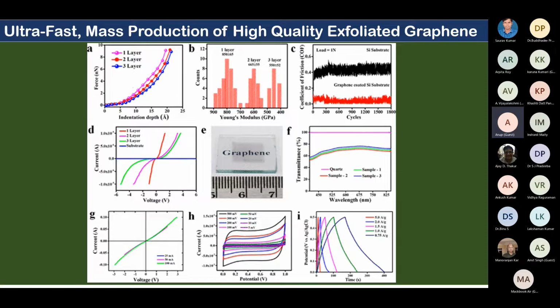And we have nicely dispersed the flakes over the pillar. Over the pillar means we took the substrate, put the flakes over it, and then tried doing the indentation over there. We have put the supplementary file detailing all the experiments, how we did this, with all the microscopic images.